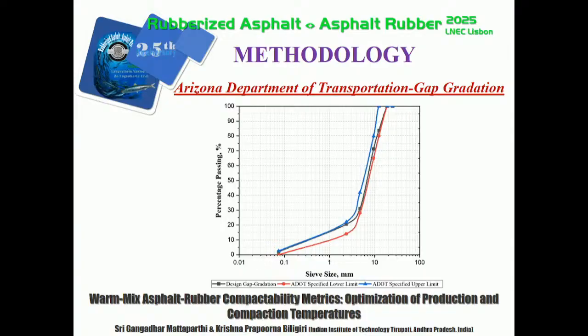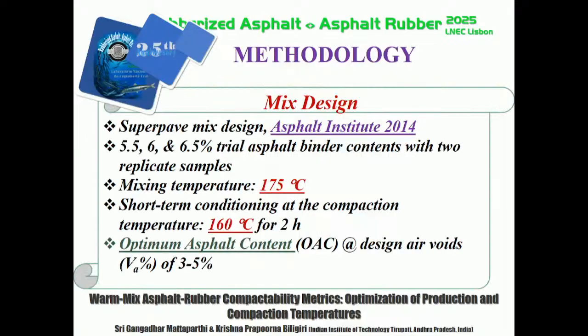For that, we adopted the Arizona DOT gap gradation, and the mix design was superpave mix design. We limited the mixing temperature to 175 based on Asphalt Institute recommendations, and the optimum asphalt content was based on air voids between 3 to 5%.